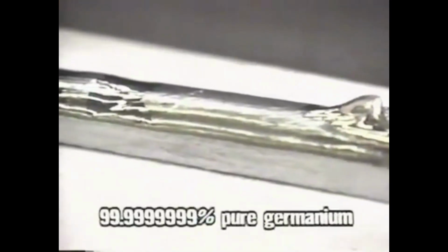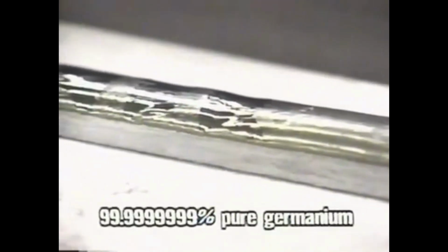This device is the same as a large microwave oven. When the high-frequency electric current sent from here flows into the coil, the germanium inside melts, and the impurities float to the top of the liquid surface. In this state, if we move the vessel slowly to the left, the impurities move to the right. When the heating coil forces the dirt to the surface, it is swept to the right edge. Then, if we chop off the right edge, the high-purity crystals are left behind.